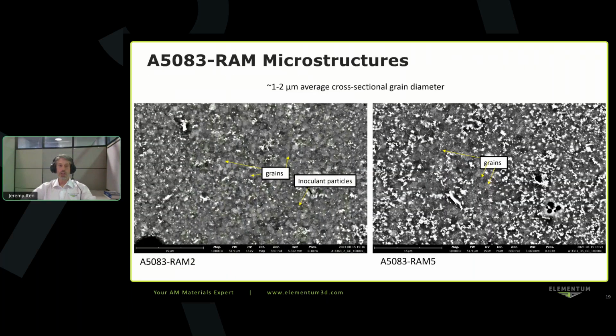Here's RAM versions of this material. There's a RAM 2, so a nominal 2 volume percent of product RAM constituents, and a 5 volume percent. And you can see now that scale bar there, if you have any trouble seeing, is 15 microns. And so the average grain size that you're looking at, cross-sectional grain diameter, is on the order of 1 to 2 microns for these materials. And you can see the nanoscale or larger, nano to micron scale product phases that are also forming. In this case, the brighter contrasted areas are largely the product phases. And you can see that there's a distribution of both micron scale, but also nanoscale product phases.